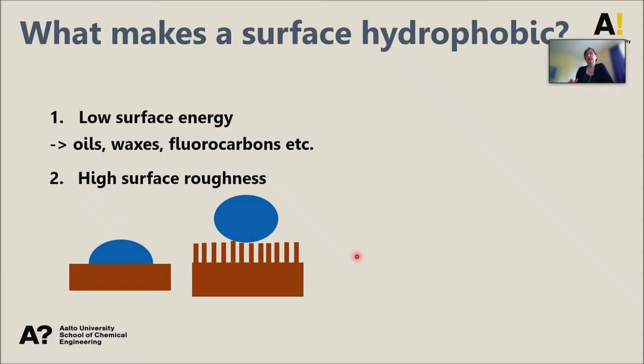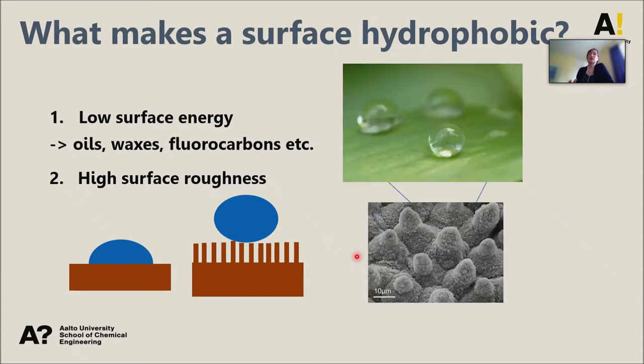And this is what was inspired by nature. If we look, for example, at the lotus leaf, you can see here that the water droplet forms almost a perfect sphere. So the contact angle of the water is almost 180 degrees. And these kinds of droplets easily roll off. If we take a microscope and look at the structure, when we study the chemistry, we know that there are some waxes with low surface energy there, but that's not enough, we also have this kind of hierarchical surface roughness. So we have micron-scale bumps that are then covered with nanoscale roughness.